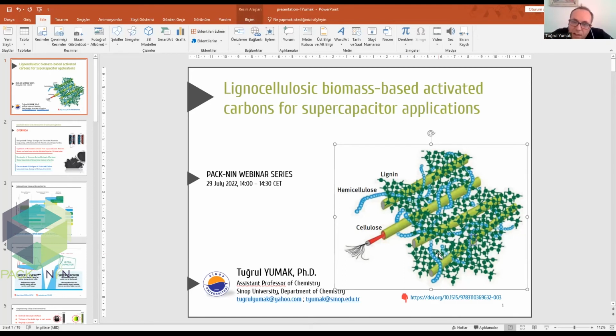In the activation process at higher temperature, we always said that this network collapses and the pores form again, but in fact it is not true. The lignin does not collapse totally and does not decompose totally. So the situation of the lignin is the origin of this 3D network. Lignin is responsible for this 3D network.